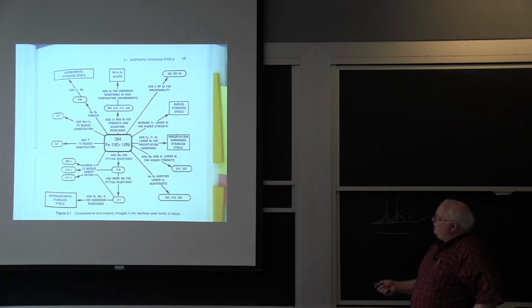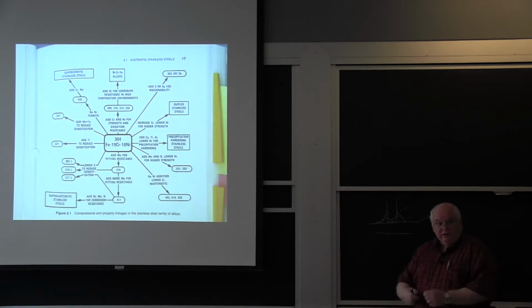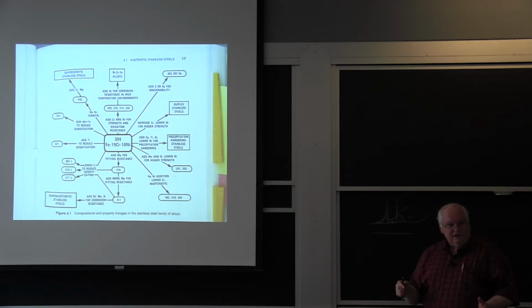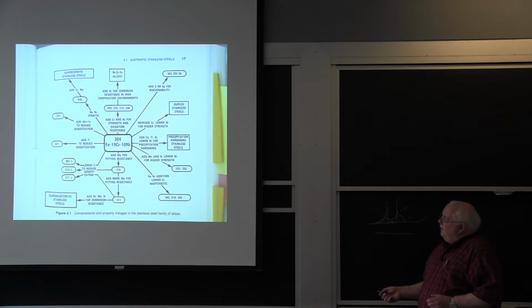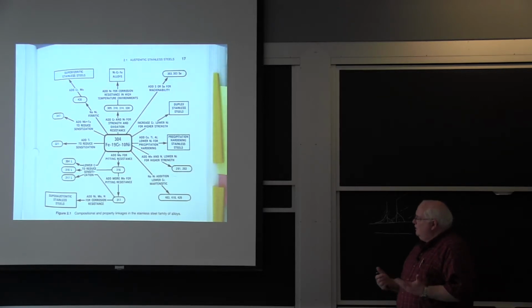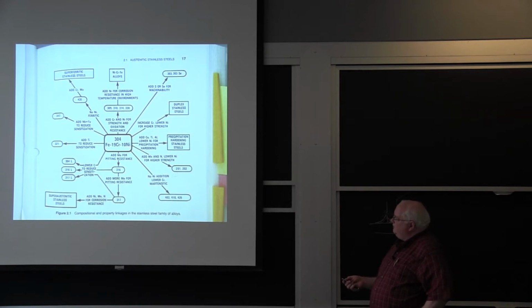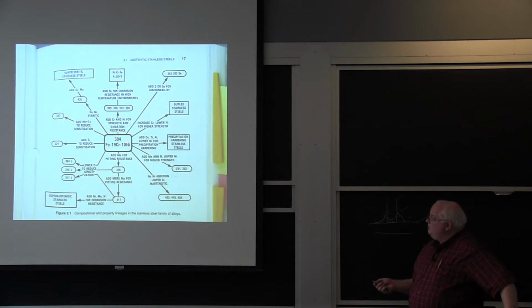Anyway, so what soon became the norm was an austenitic stainless steel 304, and Sedriks has the data in his book for about 1995, but 40% of all stainless steel made is 304 stainless. It's what we call 18-8. You go buy dinnerware and it says 18-8 stainless, 18% chrome, 8% nickel. Well, he's using 19. There's a range, and the range is 17 to 19, and it's 8 to 10% nickel. So 18-8 is what people used to call it, but now he's just using 19 chrome, 10 nickel to use the high side of the alloy content. It's weldable, and that's one of the reasons it's the most widely used. 40% of all stainless steel is 304.